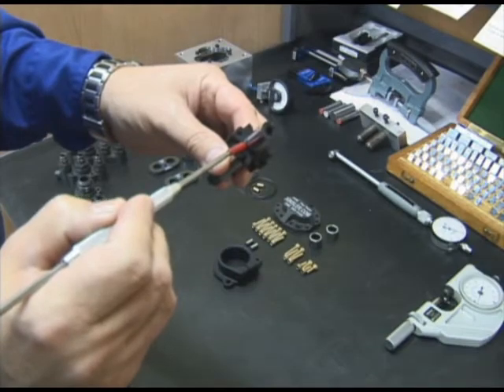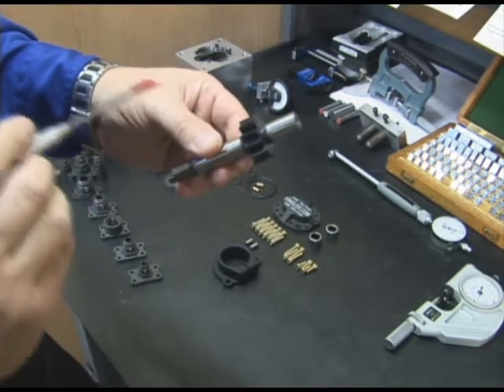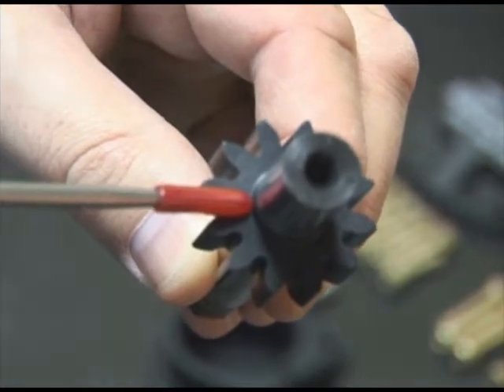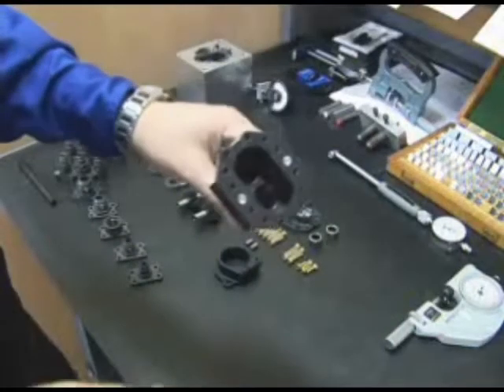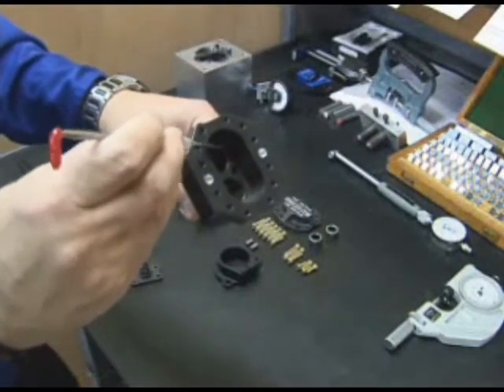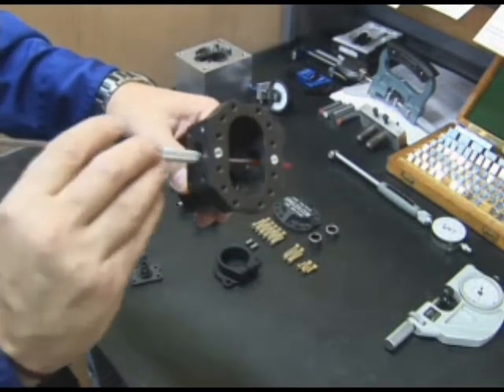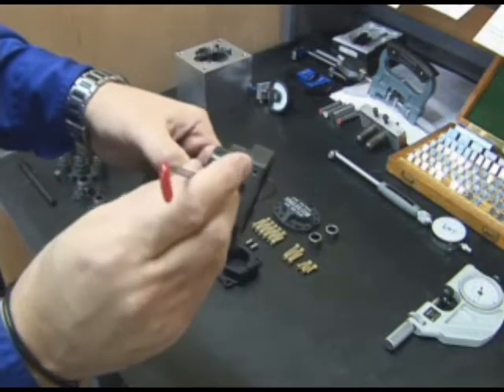The Tough Pump features a one-piece gear shaft. Combined with larger diameter roller bearings, gear teeth and shaft are high alloy steel, case hardened, and then precision ground. All corners and edges have been radiused. Straight-through design allows flow directly into gears without cavitation.